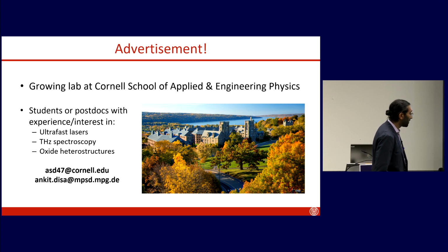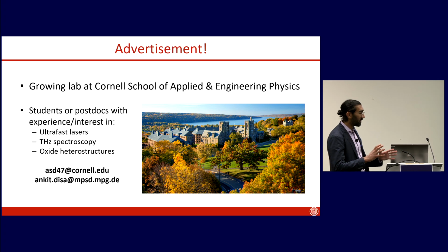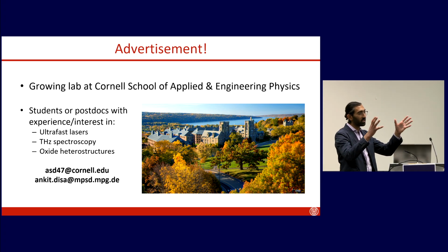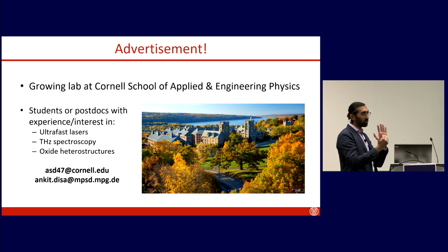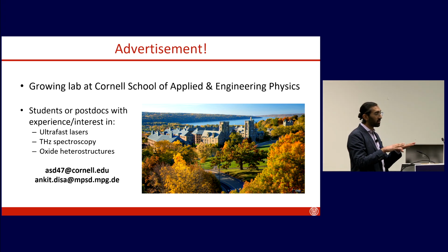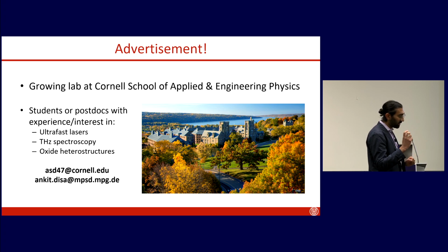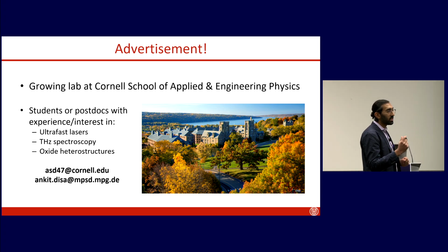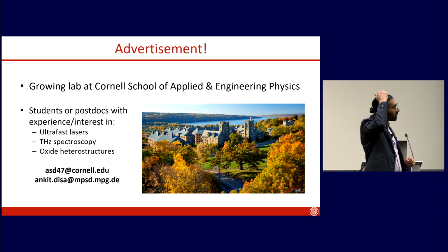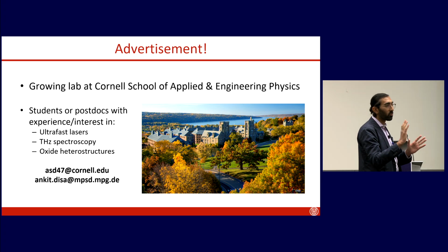Yeah, okay, understood. I think I understand your question. If you have a perfectly cubic system, and there's no structural distortion, the orbitals on each site can be chosen, let's say, at random. So you have this degree of generality. There is a small structural distortion, this orthorhombic distortion, but essentially the answer is that the orbital gap is not so big. Relative to temperature or to the spin excitation scale, the orbital gap is on the same order. And so fluctuations of the spins and fluctuations of the orbitals are still allowed in that regime, if that makes sense.